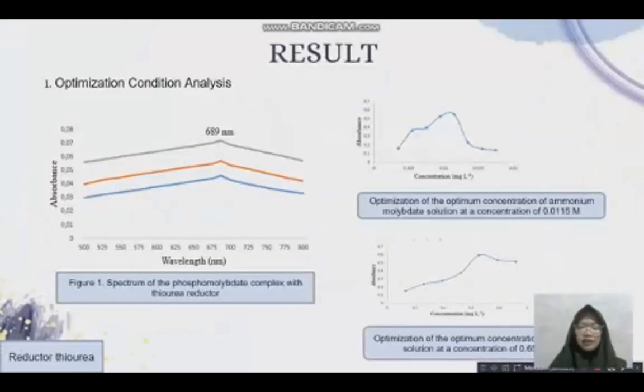Results: optimization of the analysis condition on the determination of the maximum wavelength measured by the absorption of the complex compounds phosphomolybdate in the visible area in the range of 500 until 800 nanometers. The result was a wavelength of 689 nanometers. Next, the optimization of the concentration of ammonium molybdate solution obtained is 0.0115 molarity. If the concentration exceeds 0.0115 molarity, the absorption will decrease because a new complex will occur, namely PMO.